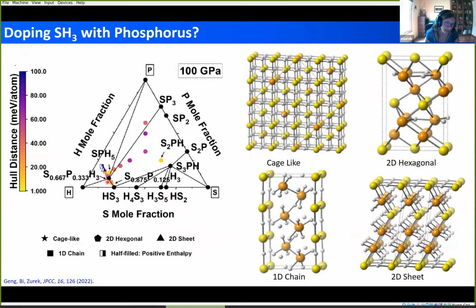Generally speaking, there were not too many ternary hydrides on the convex hull. However, there were a number of ternary hydrides not too far above it, suggesting that in principle these could be made, provided that the kinetic barriers to decomposition, as Simona just discussed, are not going to be too high.